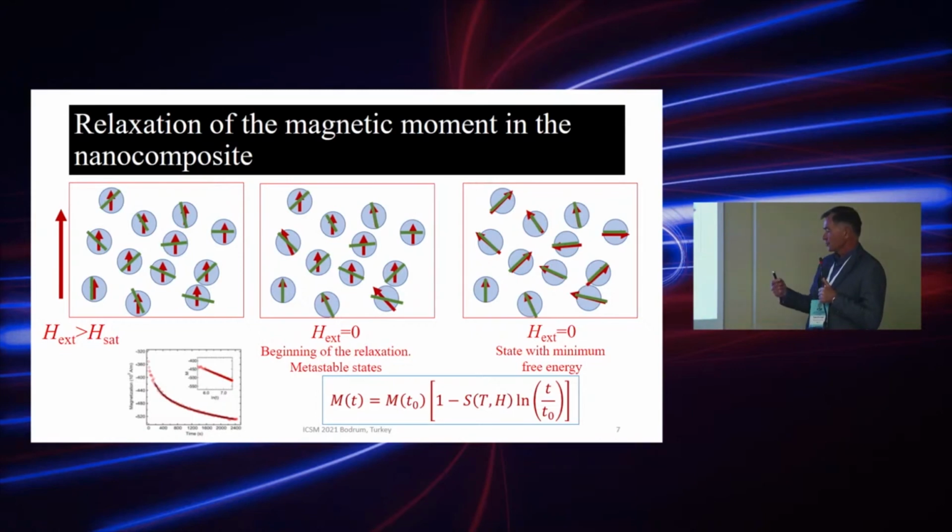Actually, in a real experiment, usually we apply not 0 but some minus 50 Oe in order to overcome the remanence of the SQUID insert, for example. Nevertheless, 0, and then the magnetization by itself starts to go to 0. And how it goes, not linearly, but via this viscosity.